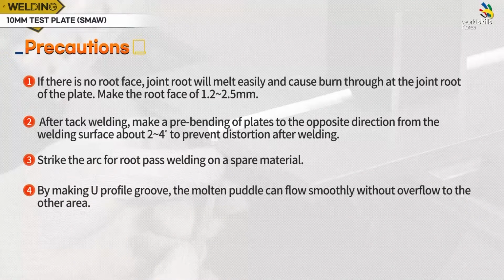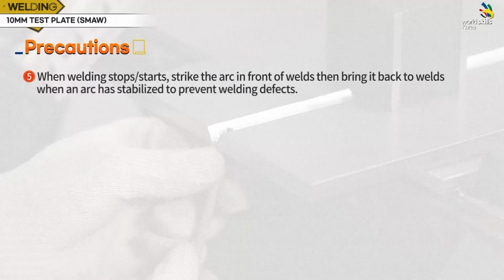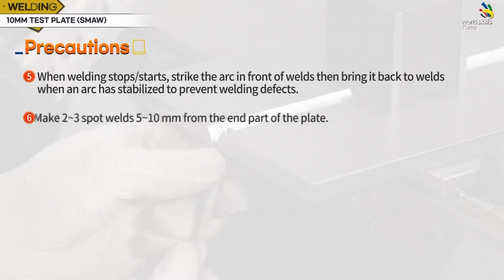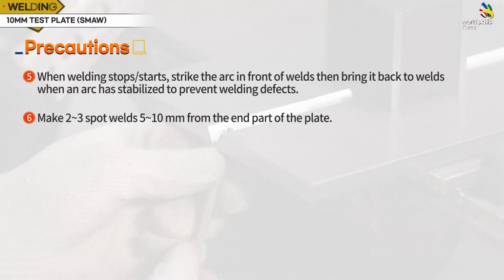By making a U-profile groove, the molten puddle can flow smoothly without overflow to the other area. When welding starts, strike the arc in front of the weld, then bring it back to the weld when the arc has stabilized to prevent welding defects. Make 2 to 3 spot welds 5 to 10 mm from the end part of the plate.